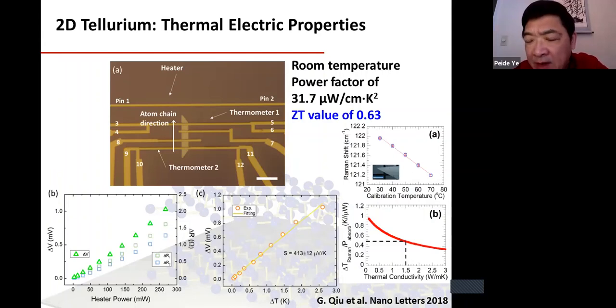around 3 to 5 nanometer. That's the region we mostly work on. Yes, but it's not the monolayer. One monolayer is still quite a challenge, because fundamentally, as you see in the Raman, the peak starts to soften. In other words, it means this material starts to reconstruct, right? The monolayer is a little bit different from, let's say, the five layer one, which pretty much sustains the original tellurium property.